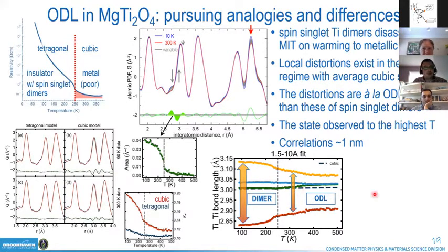However, it's not cubic, meaning it's not undistorted, which would be basically the case if all the data collapsed into this dashed line, suggesting that a very similar set of events takes place as in iridium spinel.